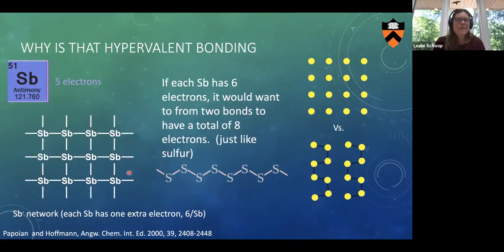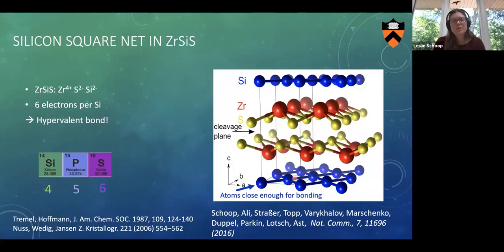But these square nets exist in solids. An example is zirconium silicon sulfide, which has such a square net, and it has six electrons per silicon. So we can count the electrons as I did up there, and then I get a silicon two minus. So silicon has four electrons plus two, gets me to six. So it's again just like sulfur. So there must be a hypervalent bond in the square net for it to be stable.